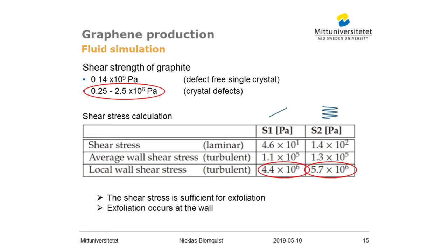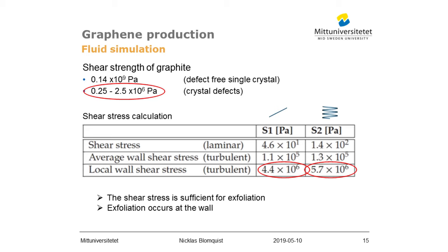We then use the simulation data, the fluid velocities, to calculate the shear rate or shear stress in this system. And this was what we found. We saw that the shear stress from the helical coil shaped tube was higher than in the straight tube. We also saw that the turbulent wall shear stress was much, much higher than the laminar shear stress contribution, about 3 orders of magnitude. But the most interesting thing here was this.